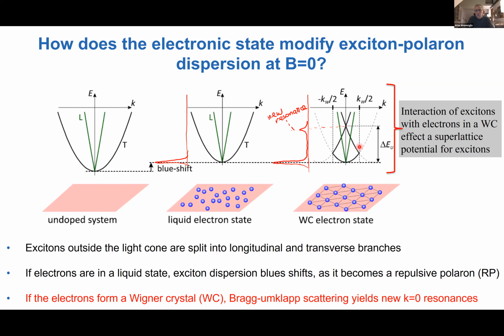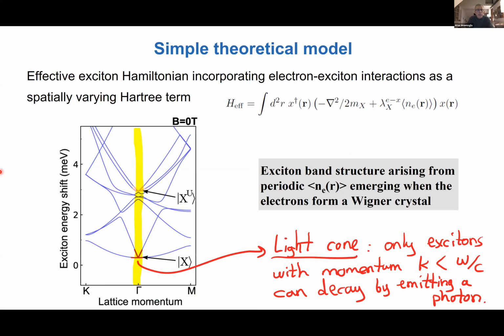Now, this is a very simple 1D model. In general, of course, we have a 2D problem, and we can calculate the excitonic band structure in the reduced Brillouin zone by making a simple assumption where we treat the electrons as presenting a spatially varying potential on the excitons. And you can see that there are a total of 12 excitonic bands, and 6 are high in energy, and then of the lower 6 ones, 2 of them